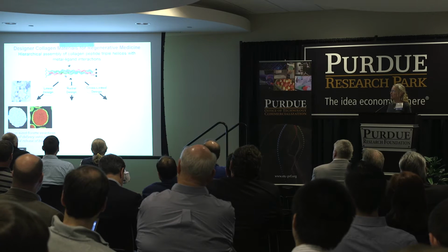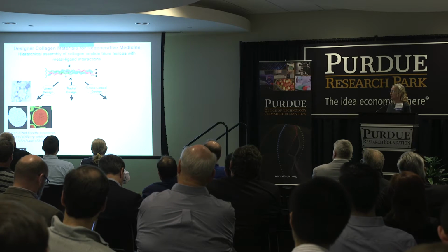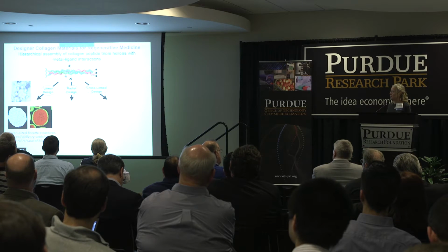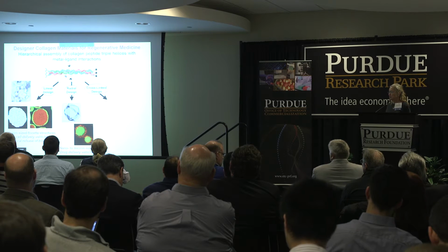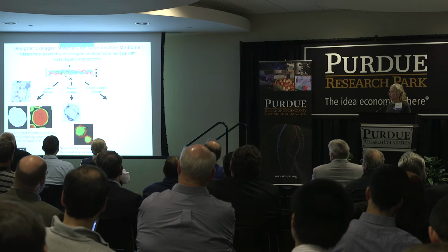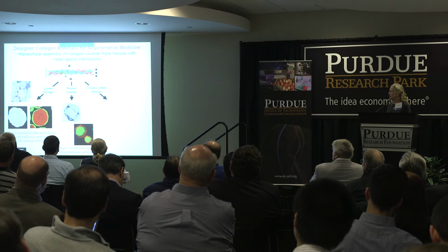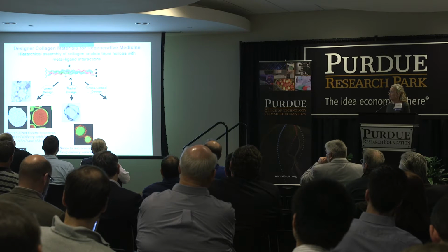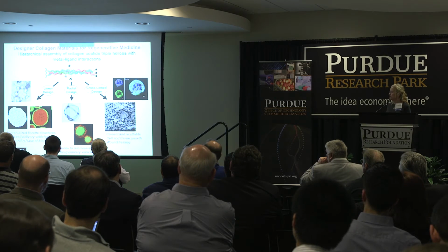In the radial design, if we have our metal-ligand interactions in the center, we can get this small collagen peptide to further assemble into hollow cages. And these hollow cages we can decorate either on the outside through chemistry or the inside through encapsulation as drug delivery vehicles. And if we have our ligands for the metals either at both the inside and the exterior, we can get to highly cross-linked materials.